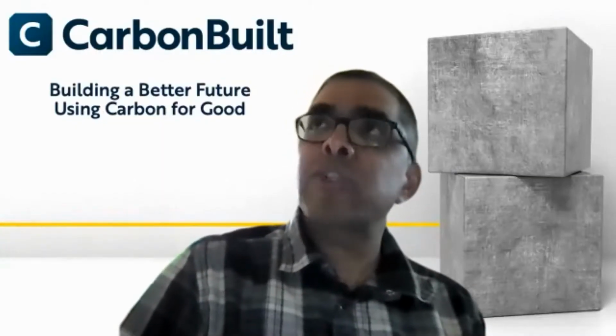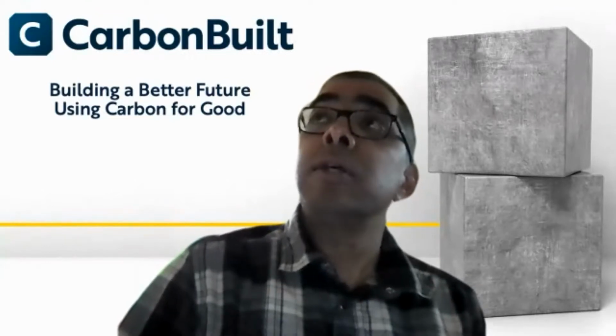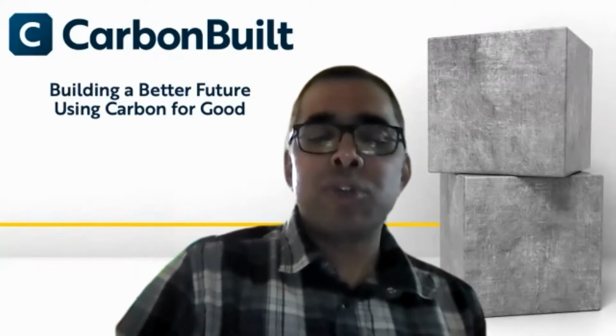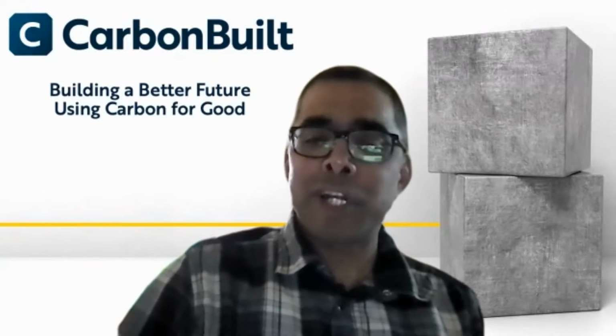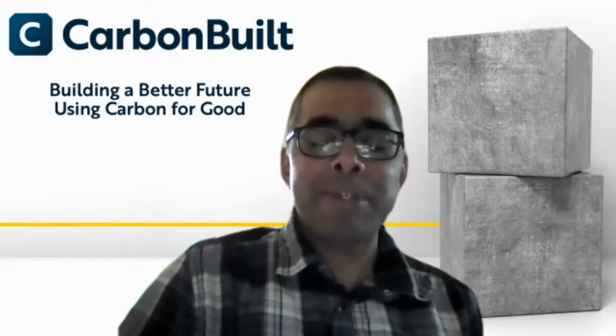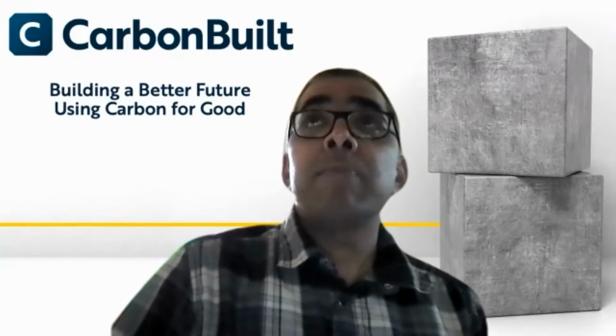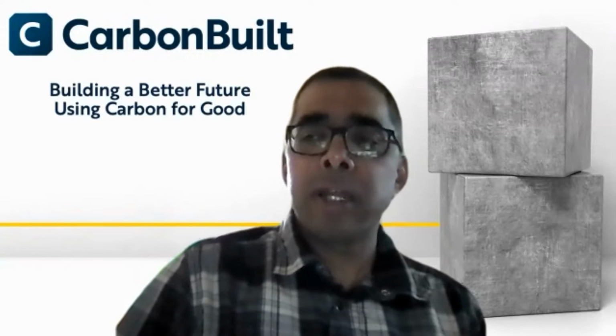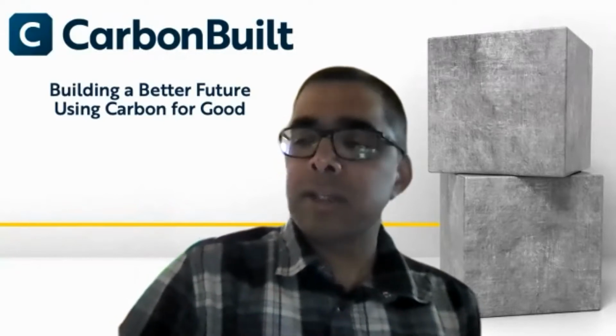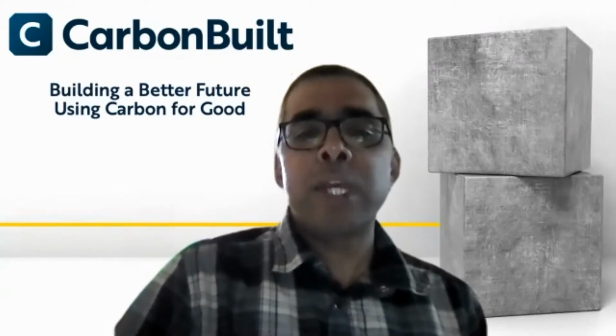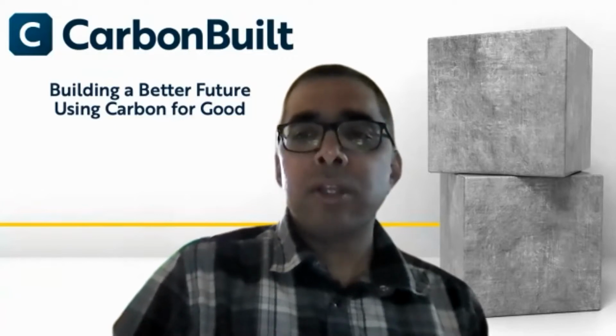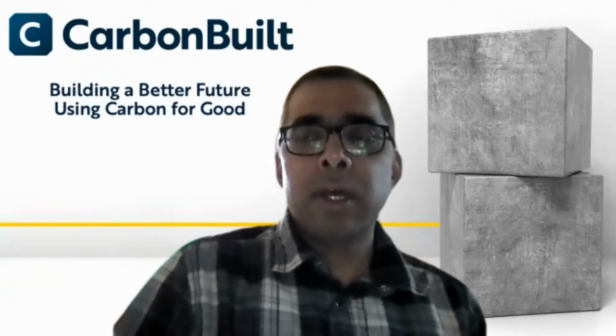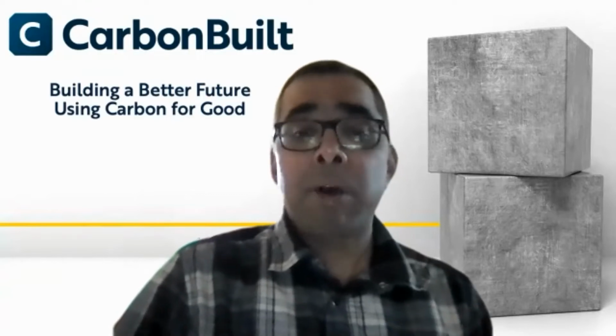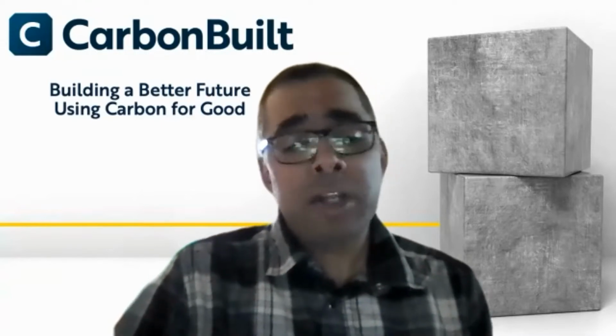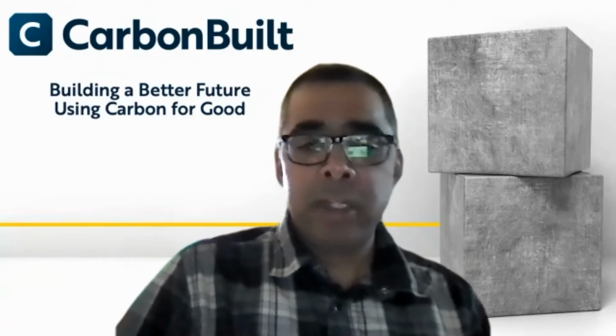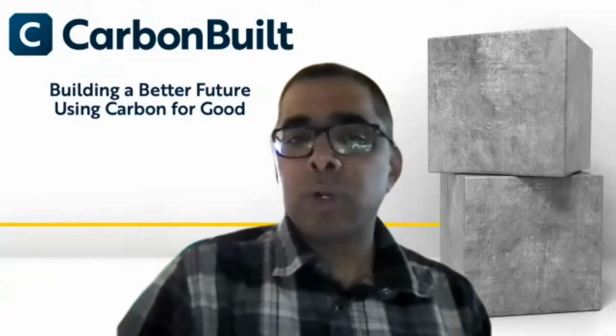Yeah, it's a great question. I think that's one of the challenges in thinking about this long duration carbonation as a source for CO2. You'll see this from the cement industry these days, talking about it as trying to take credit for the long duration carbonation that happens. And the challenge is that as you remove calcium hydroxide, or it's carbonated, you get a slow drop in pH, right? So it's that more acidic nature that is the problem. In our case, it's a very controlled process, right? So we can tailor the process so that when you're done curing, you either can have a buffer of calcium hydroxide if you want one for reinforced product, or if you don't have reinforced product, and obviously like block, for example, most of it is used unreinforced, we can carbonate away all the residual calcium hydroxide, so that's not an issue.